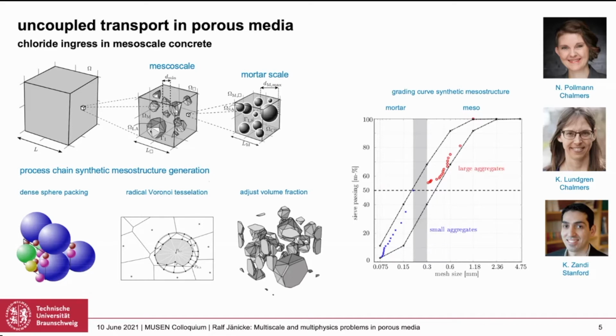And typically what is observed is that there's a layer around those aggregates which is somehow pre-damaged, which comes from the shrinkage during the solidification of the concrete. And this zone is pre-damaged and typically has a higher porosity. And that's typically a zone where the diffusion of the chloride ions takes place in the absence of fractures at that stage. And since this is a surface effect that's also size dependent, the more small particles I have, the more surface I have, and the higher one can expect the effective conductivity for this